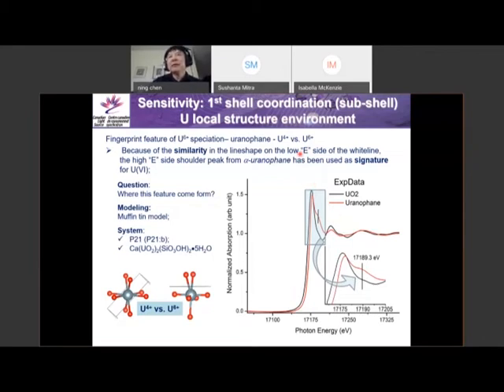So these 4+ versus 6+ correspond to two different first shell coordination polyhedra. 4+ is like this, and then this is 6+. The more difficult thing here, experimentally, is that the edge jumps of these two spectra are exactly parallel to each other. So we cannot use the commonly used way in the existing first derivative to determine the coexistence of the two oxidation states. But we have another way, by this shoulder. For this case, I will address this shoulder peak here, 17189, related to the structure component.